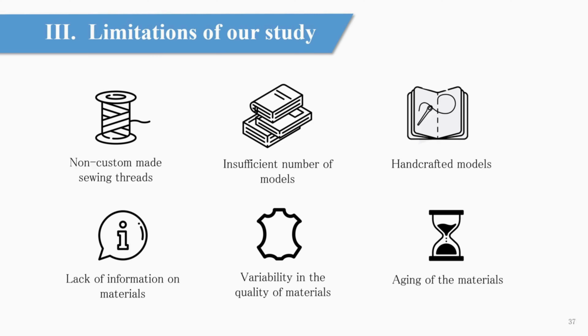That's why developing custom-made samples tailored to specific experimental needs is a promising direction. It will allow us to better understand the impact of each characteristic on the performance of threads and cords used in sewing. The main limitation of the study conducted by the conservation studio is the insufficient number of models used during the mechanical fatigue test. The time required for each model to pass through is between 13 and 20 hours, and the limited endurance of the test bench forces us to reduce the number of models per type to 3. This doesn't allow for good repeatability of the results and therefore requires them to be approached with caution.